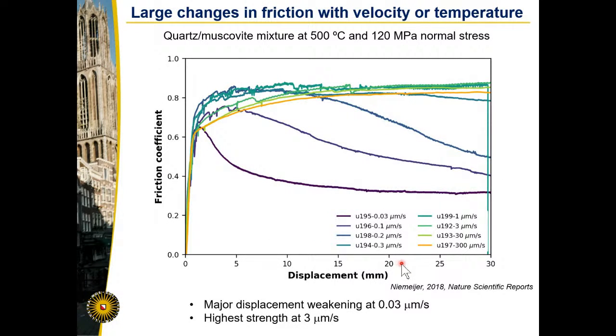Does this happen in the real materials as well? This is quartz muscovite at 500 degrees. The slowest experiment here is 30 nanometers per second, and you can see this really pronounced weakening. This experiment lasted 10 days. You can imagine that we don't want to do too many of these experiments.